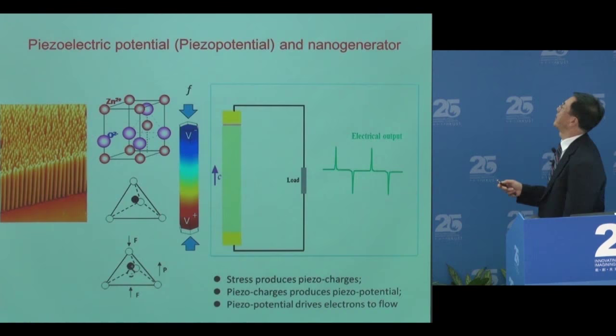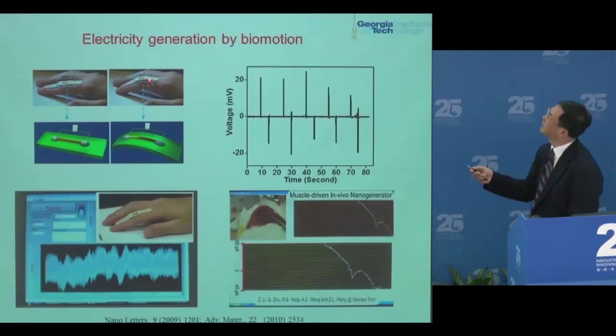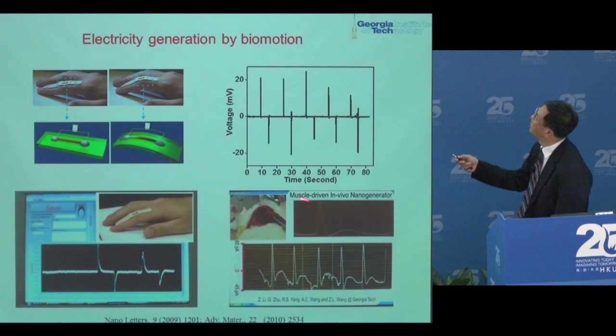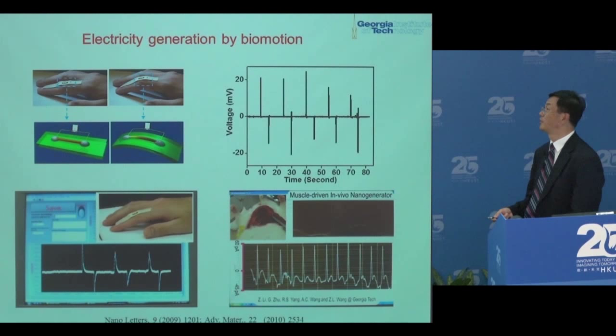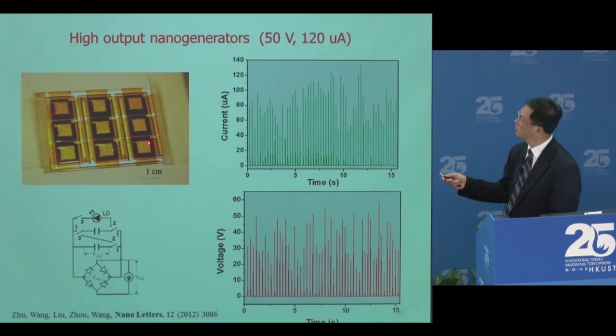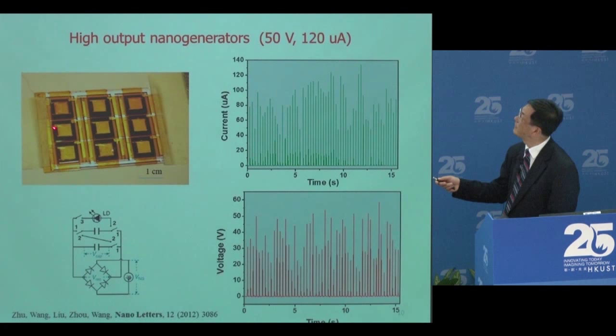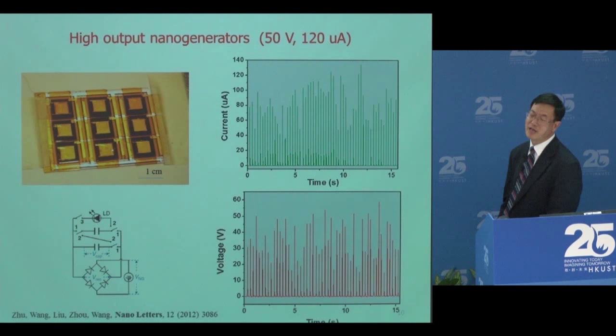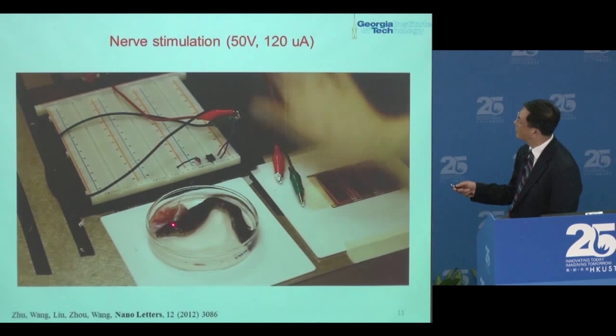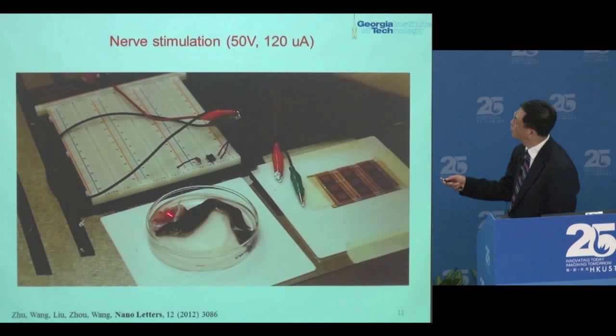A few years ago, using a single nanowire placed on a finger edge, we were able to generate a few volts. We also demonstrated using the heartbeat of a small animal to generate electricity — small, but for the first time. This was the piezoelectric effect. We continued to develop, using a substrate to grow nanomaterials, fabricate devices, put electrodes, and package together. These devices can give about 100 microampere current and 50 volts — much higher than at the beginning. Using this, we can stimulate biological species: a frog leg still alive — when the electrical signal triggers it, the leg jumps back and forth.